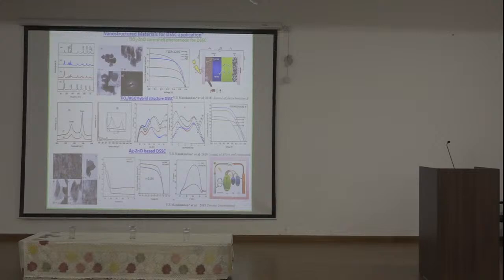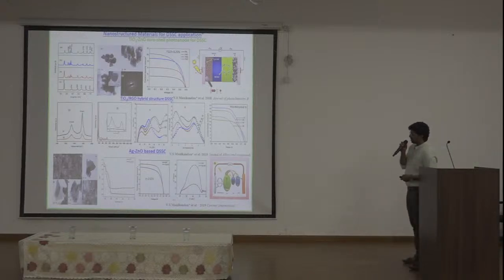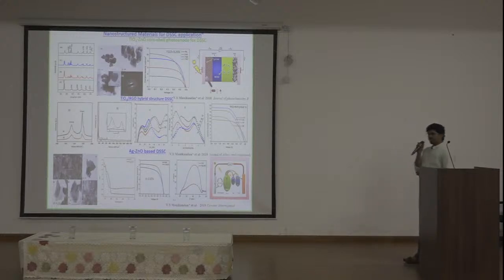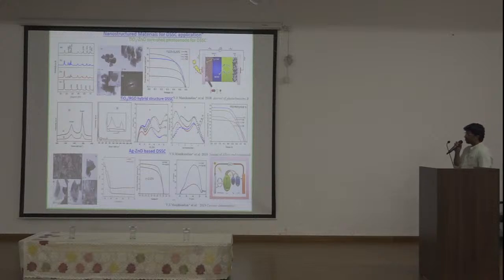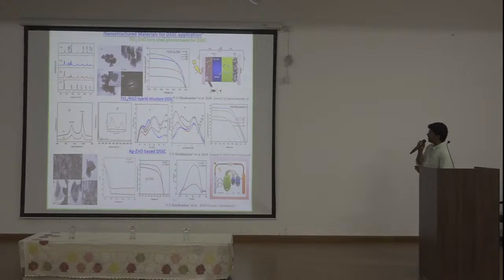We can see this is the basic characterization: GO, reduced graphene oxide, and the TiO2 composite, showing the D and G bands. And here we have checked the impedance over the frequency region, from higher frequency to lower frequency. We get the semicircles. Initially, the first semicircle is the counter electrode charge transfer resistance, but the middle semicircle indicates the charge transfer resistance from the dye molecule and semiconductor material to the electrolyte.